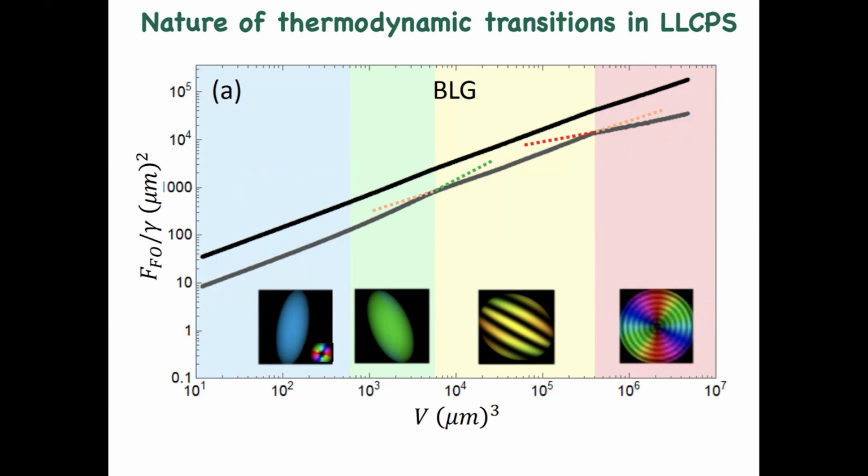So this is all the elastic part plus the anisotropic. And you see, there is a change in slope versus the volume. At least you can capture that here and here. So that tells you that this is actually a first order thermodynamic transition. And the reason for that is that really this is a two-phase system. The anisotropic part of the surface tension is finite, not zero.